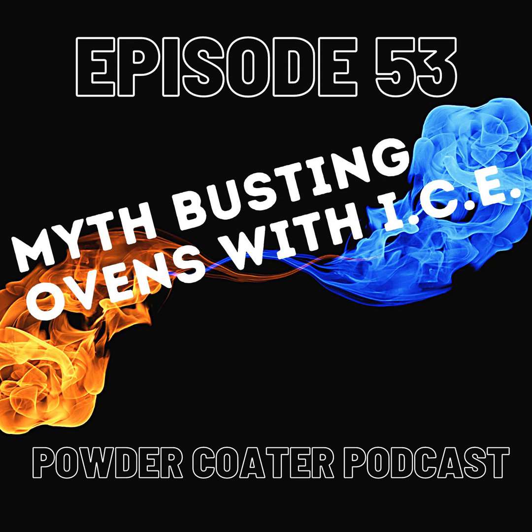the one thing, and I do this a lot with new customers, because, we want reclaim. I said, that's great if you're a high volume, but the systems we're putting in are not high volume where you're going to see a true benefit to reclaim. And then you start to explain to them, well, technically, if you read all the data, you're only supposed to reclaim powder 3 times before you throw it away. Right. So if I mix and reclaim with my virgin powder, how do I know which particles were in there only twice, and how, so how do you sort that out? Leads to a lot of problem solving and chasing tails, right?